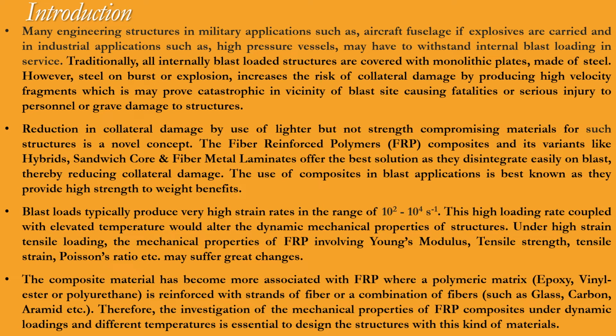Blast loads typically produce very high strain rates in the range of 10^2 to 10^4 per second. This high loading rate coupled with elevated temperature would alter the dynamic mechanical properties of the structures. Under high strain tensile loading, the mechanical properties of FRP involving Young's modulus, tensile strength, tensile strain, Poisson's ratio, etc. may suffer great changes.